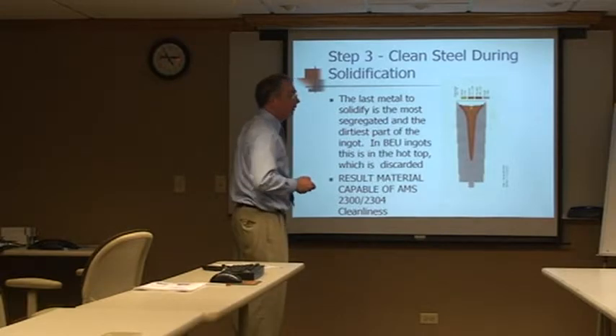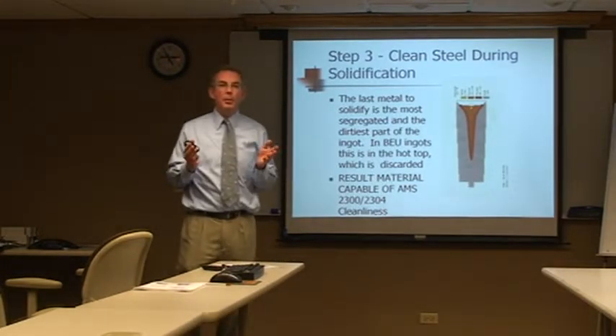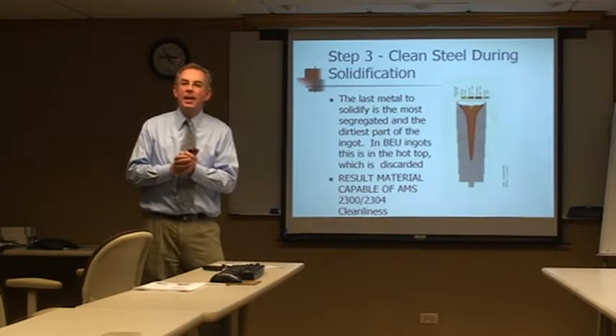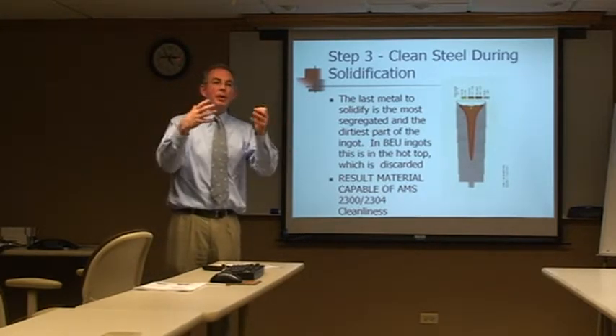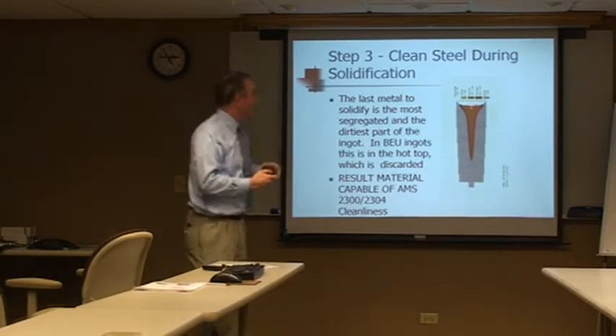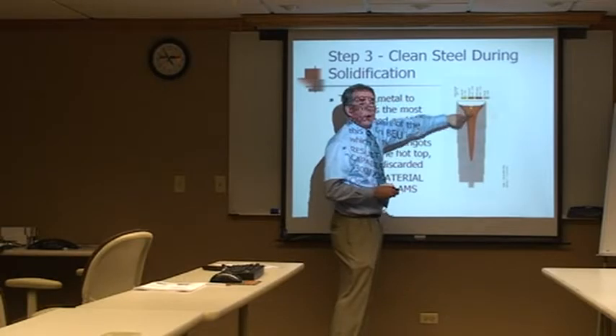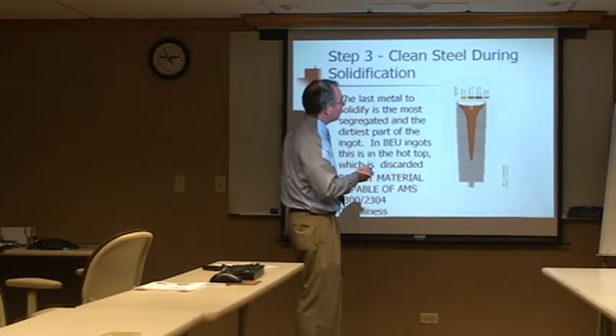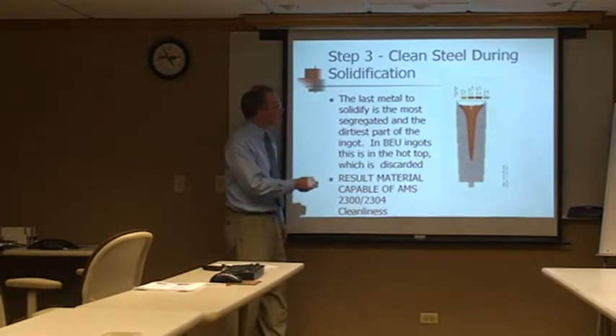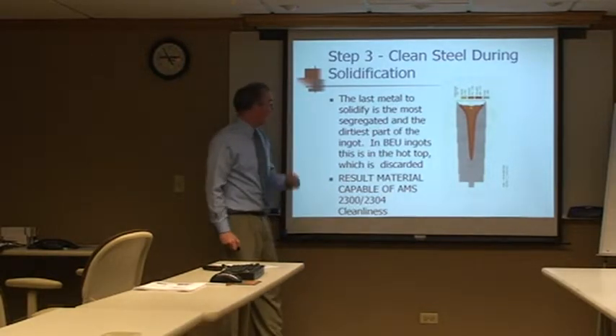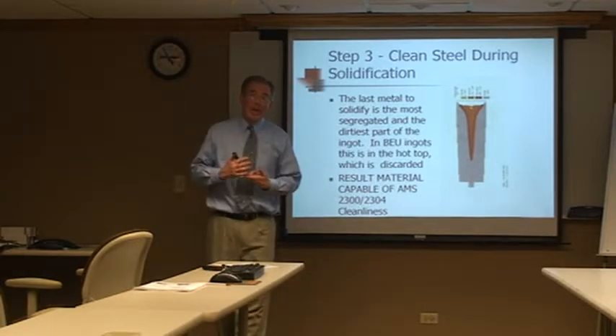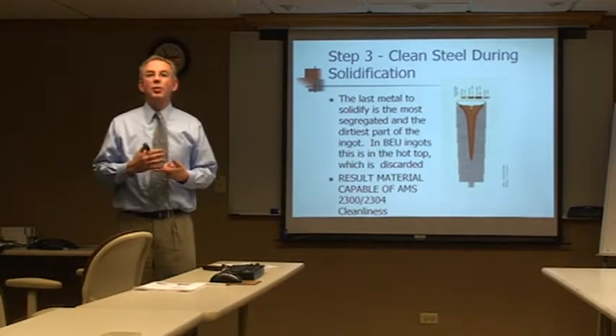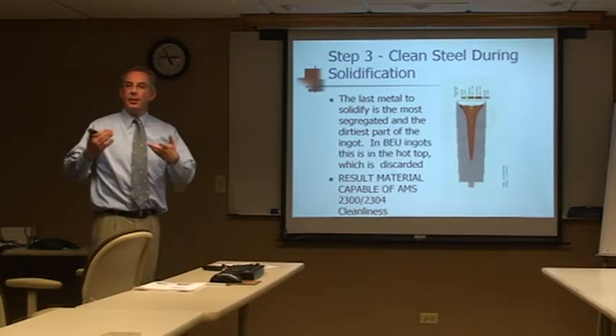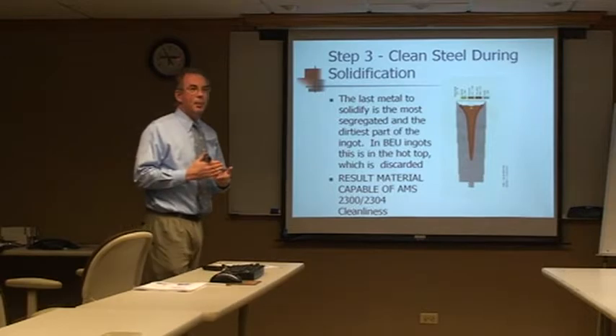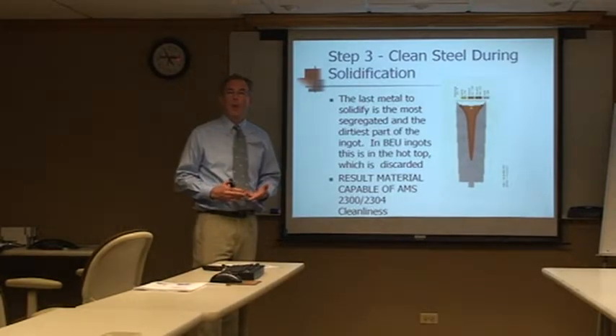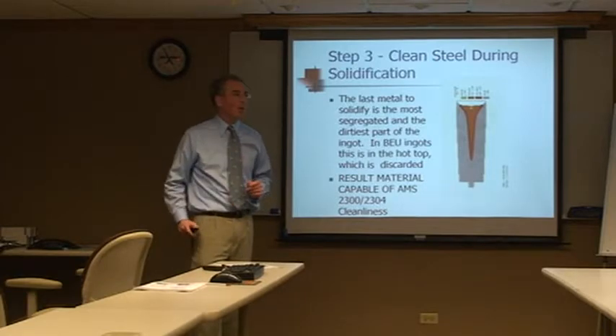Last metal to solidify is very important, because the last metal to solidify is where all the impurities, the most highly segregated part of the ingot, and most of the inclusions are going to get pushed with that solidification front. So if we can have the last metal to solidify up here in the hot top junction, we know that everything else below that junction is going to be very good. The result is an ingot that, once forged, is able to produce approaching remelted cleanliness. You're going to have AMS 2304 if you're familiar with the premium quality spec, and 16th inch flat bottom hole flaw sizes. So very, very high quality.